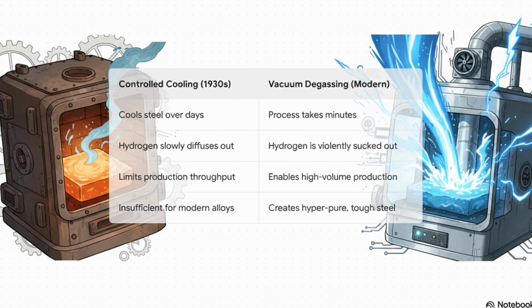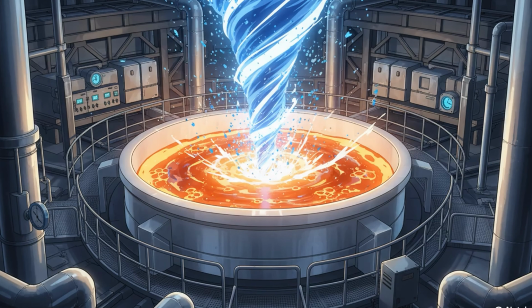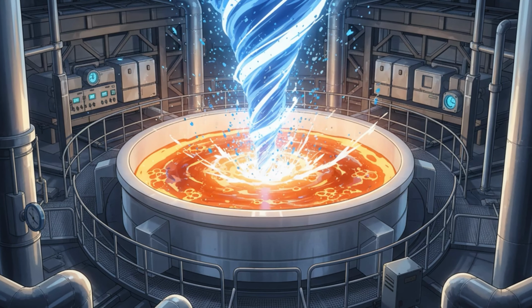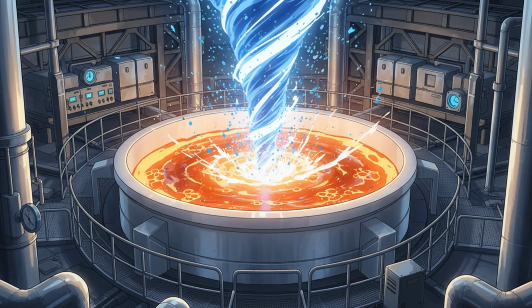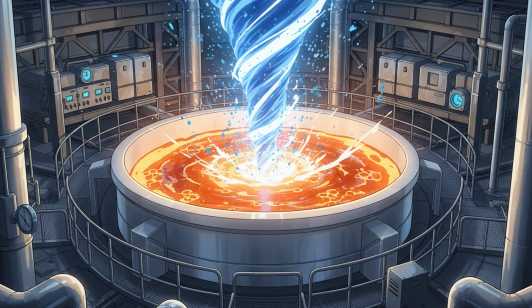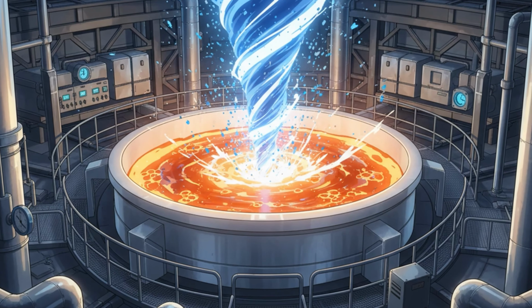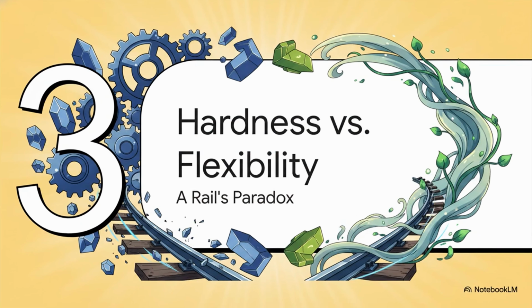Not only does it suck the hydrogen content down to a super safe level, we're talking well below 1.5 parts per million, it also rips out other unwanted gases, like oxygen and nitrogen. This lets them do something called vacuum carbon deoxidation, which cleans the steel without having to use additives that could create brand new flaws. So what you end up with is this hyper-pure, incredibly tough steel that's perfectly primed for high-speed rail.